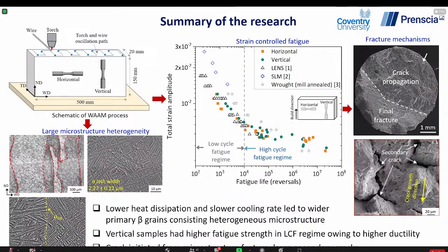So I'm just showing a summary of the overall research we have conducted. We have used a wire and arc additive manufacturing process with Ti64 as raw material. And we built these materials using an oscillation build strategy developed for the WAAM process. So basically in this oscillation build strategy, you can oscillate your wire and the torch along the wall thickness direction, where the travel direction is along the wall width direction. We have tested the materials in both horizontal and vertical orientation with respect to the deposition layers.